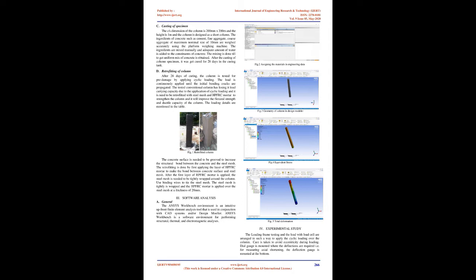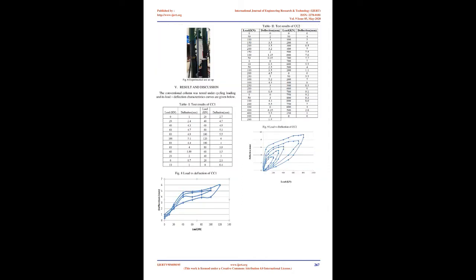A steel wire mesh is made up of uniformly crossed stainless steel in regular patterns, and it has the thickness of 0.15 mm and the size of openings is 25 mm. High-performance fiber-reinforced composite is developing quickly to a modern structural material with a high potential. Fiber-reinforced concrete, FRC, is concrete containing fibrous material which increases its structural integrity. It contains short discrete fibers that are uniformly distributed and randomly oriented.